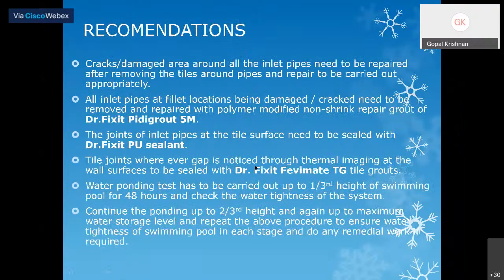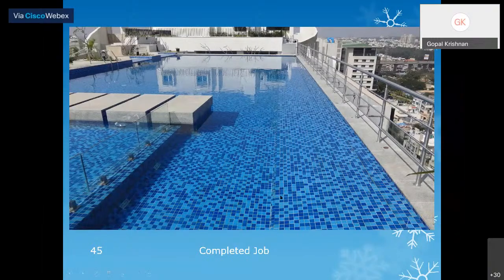The source of the leakage was detected, and we asked the contractor to do the grouting in certain areas, and also take proper measures by applying polyurethane sealant, some grout, and the tile joints to be fixed properly. Everything they have done. Then stage-wise, they filled up the swimming pool and observed whether any leakage was coming further or not. Okay, this was the completed job. It was quite satisfactory.